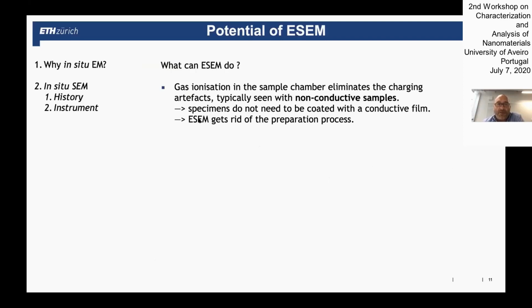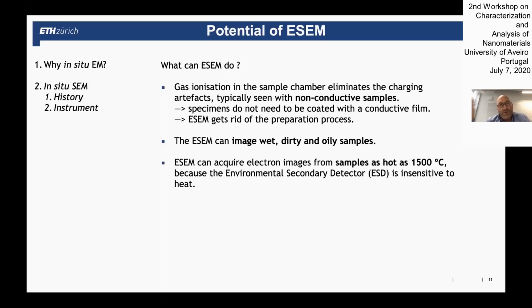So this is really good, and this allows you to work fast without much preparation. And in fact, many tabletop microscopes, these tabletop SEMs, they have this mode implemented automatically. So you can really introduce a bit of gas just to prevent charging of your sample. Because you can play with the pressure range, you can work with wet samples and study liquids even in the scanning electron microscope. This is beautiful if you want to study any crystallization processes, for example.